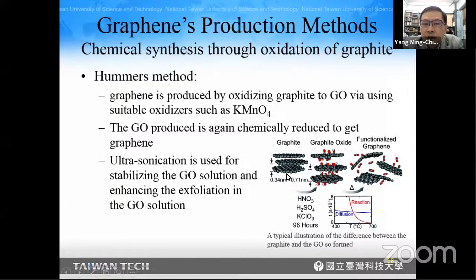And here, this figure shows that in the beginning we have the graphite, and after treating with these chemicals, oxidizing it in these chemicals for 96 hours, the graphene layers will have oxygen produced, and this will expand the space between the layers. And then after reduction, we'll obtain pure graphene. And after that, in order to disintegrate this graphite, ultrasonication is used to stabilize the graphite oxide solution and enhance the exfoliation of the graphite oxide.